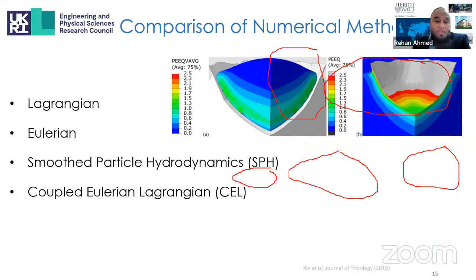Coupled Eulerian Lagrangian provides a better balance between accuracy and large-scale deformations. In this technique, the Lagrangian is usually the substrate. However, in cold spray coatings, the substrate can also undergo large deformations, and there are chances of abnormal deformations in the Lagrangian mesh. Hence, CEL is better suited for thermal spraying rather than modeling of cold spray coatings.